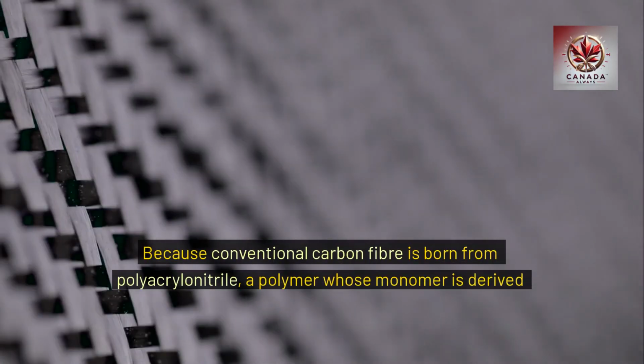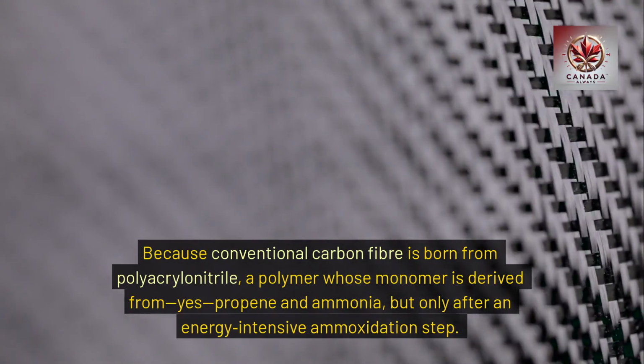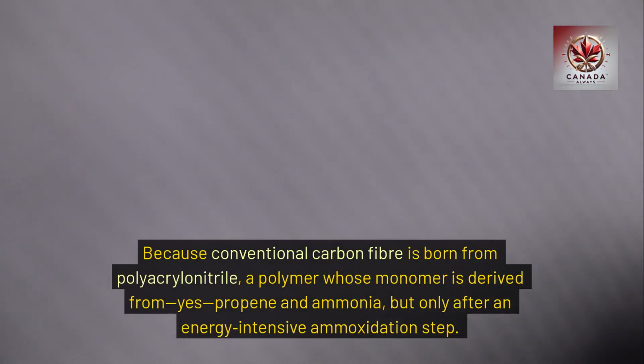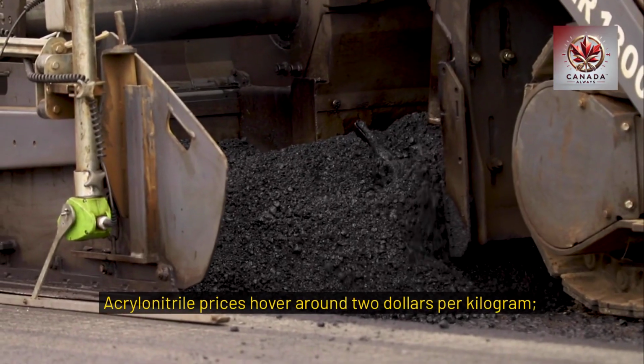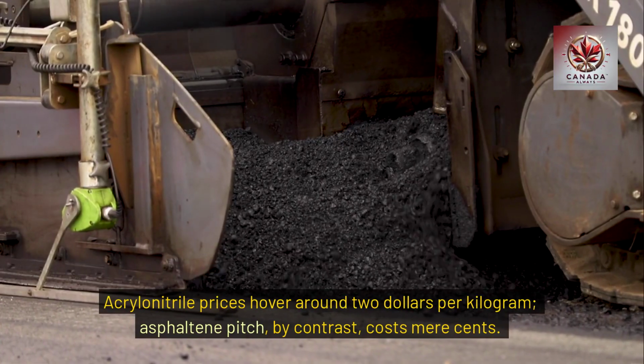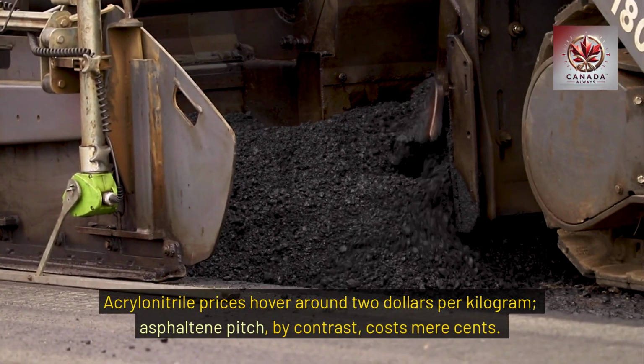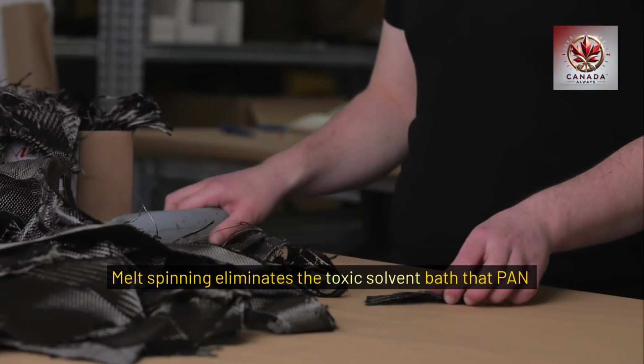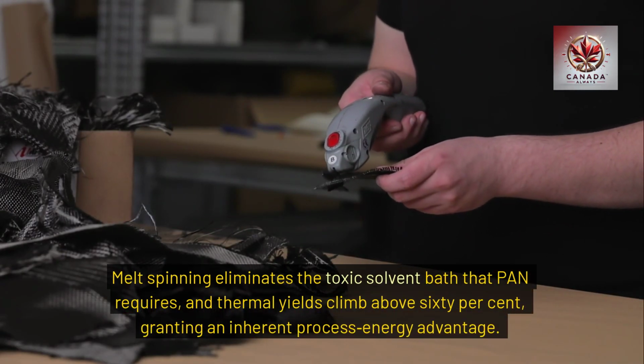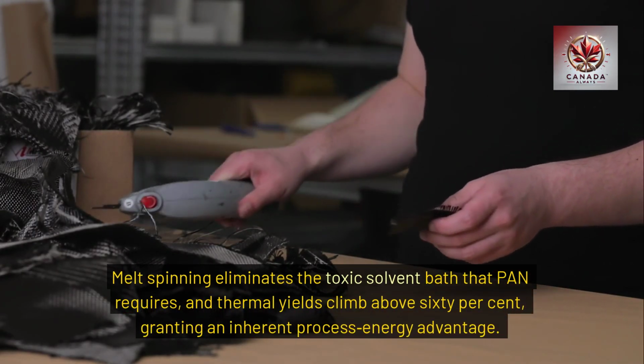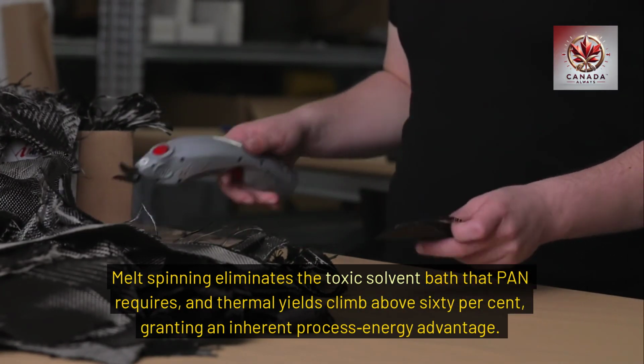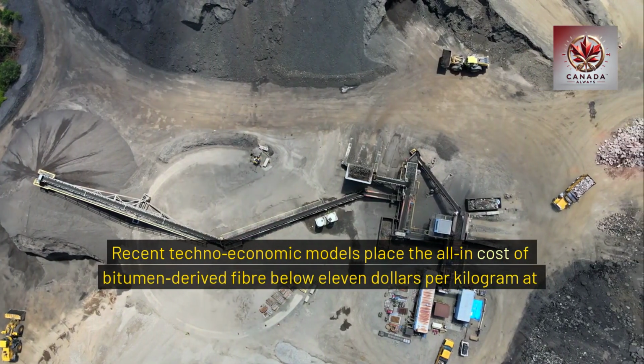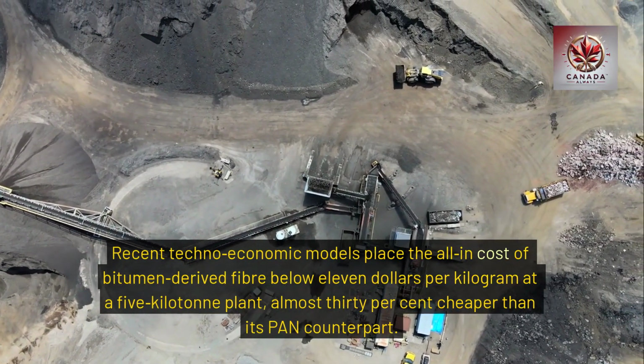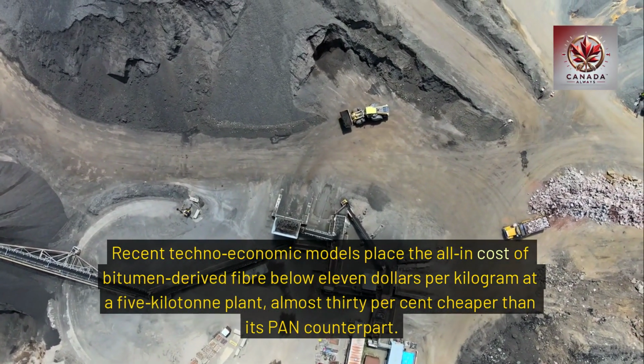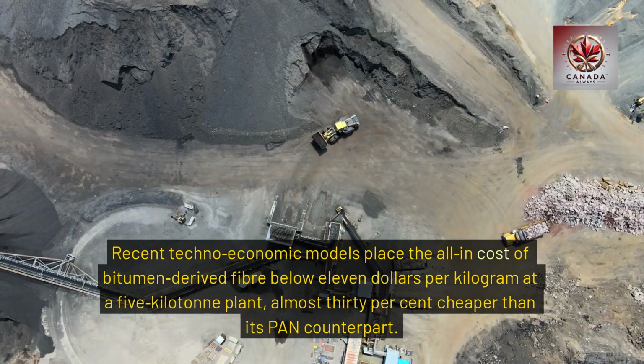Because conventional carbon fiber is born from polyacrylonitrile, a polymer whose monomer is derived from, yes, propene and ammonia, but only after an energy-intensive oxidation step. Acrylonitrile prices hover around $2 per kilogram. Asphaltene pitch, by contrast, costs mere cents. Melt spinning eliminates the toxic solvent bath that PAN requires, and thermal yields climb above 60%, granting an inherent process energy advantage. Recent techno-economic models place the all-in cost of bitumen-derived fiber below $11 per kilogram at a 5 kiloton plant, almost 30% cheaper than its PAN counterpart.